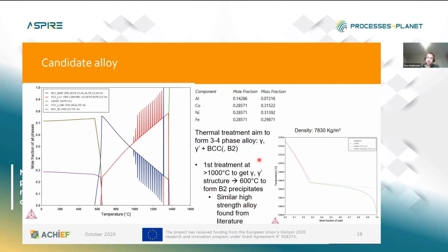So we aim for this with this heat treatment. We aim for this gamma prime plus this BCC B2 structure. So this 4-phase structure should, at least according to literature, have quite good strength and elongation properties.